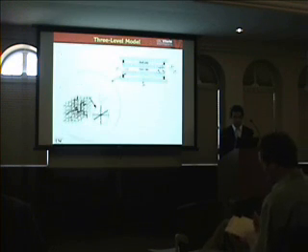So for doing that, we developed a three-dimensional network, in which the pore radii of the network are distributed according to the pore size distribution that is generated by the computer, and is pretty well matched by our experimental pore size distribution. We study the effect of connectivity of the pores and thickness of the network, and the effect of pore blockage is also taken into account. So the simulator can monitor the pore size distribution during the deposition of the triisopropylsilane.